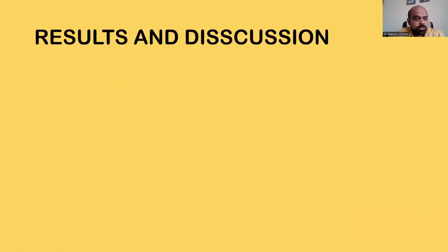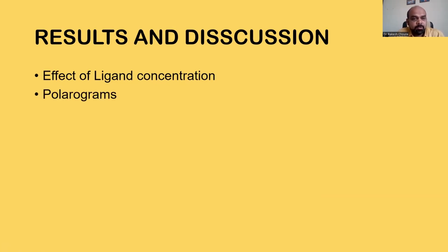Now come to the result and discussion section. So here I am talking about the effect of ligand concentration on polarograms and complex formation. In this section, atropine and its complex gave a well-defined cathodic reduction wave at pH 8.2 with 1 molar borate buffer solution. The plot between Id, that means the current, and voltage yielded a straight line in each case, passing through the origin, confirming the diffusion controlled nature of the reduction process.